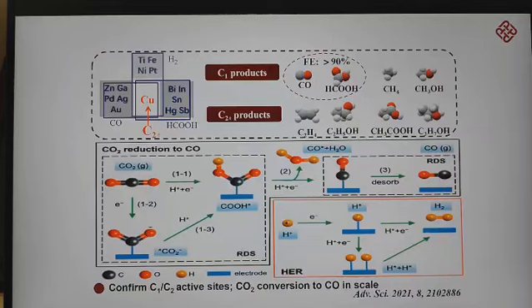On the other hand, C1 products involve a 2-electron transfer process with a simple reaction pathway. Currently, the Faraday efficiency for CO and formic acid can both exceed 90%, making the large-scale production of CO from CO2 feasible.